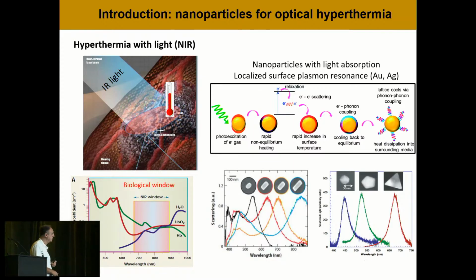And why is it important to use near-infrared? Because near-infrared is the so-called biological window. What it means is that in this region, the body absorbs the least amount of light. So light can penetrate much deeper in this region than in visible light. And that is very easy to see. If I do this with a green laser, nothing comes out. If you try the same with a red laser, you'll see the spot here. So as we go to the infrared, more light penetrates into our body.